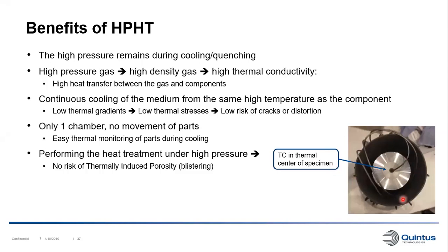So this is a setup in our smallest furnace in our lab in Sweden. Here we have a relatively large sample compared to the furnace. And here we can see that I put thermocouples in the gas around the component. I have one thermocouple on the surface of the component, and I've also put one thermocouple in the center of the component here with this drilled hole. So it's very easy to monitor the temperature in different parts of your component for process validation and research, etc. So you know exactly what cooling rate you had in different parts.